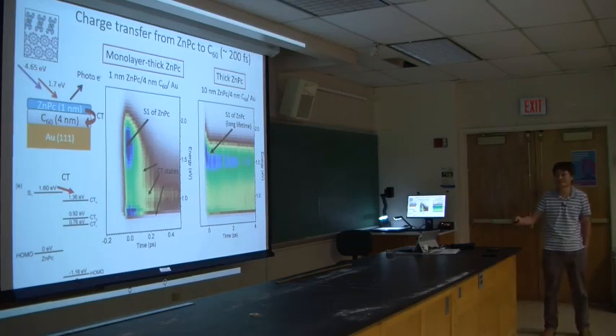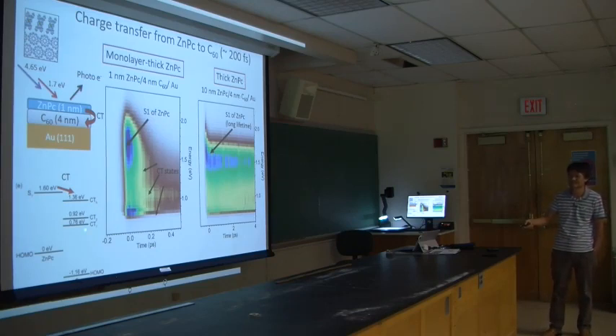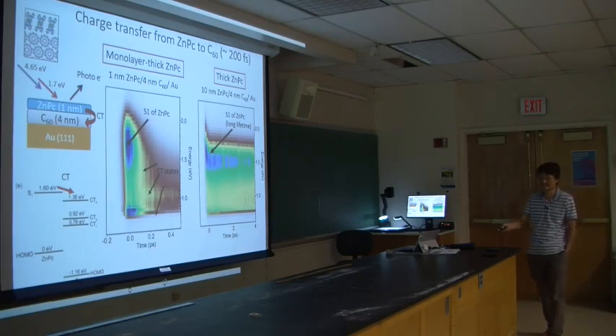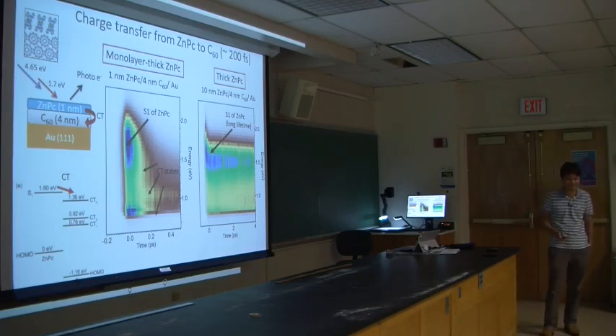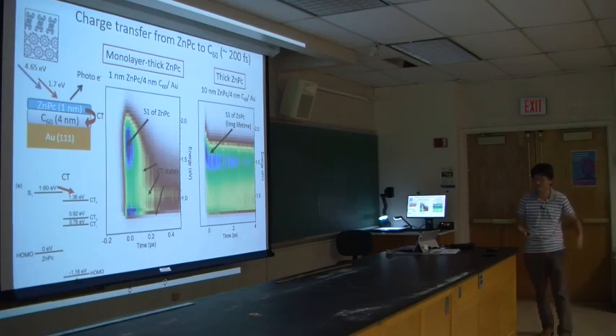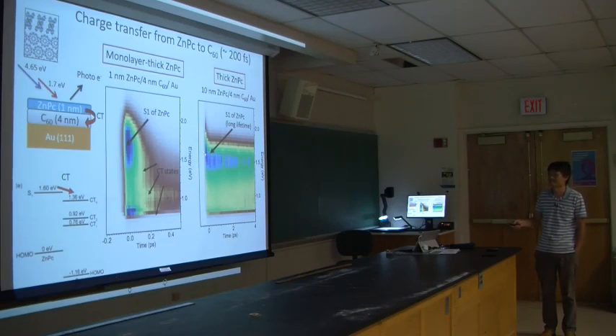So now we can already map out the band structure for these CT excitons, right? You have different energies that represent different CT excitons with different spatial delocalizations. So here's this control experiment. If we just have ZnPc, the singlet state has a really long lifetime. Anyway, we are interested in this CT state, right?